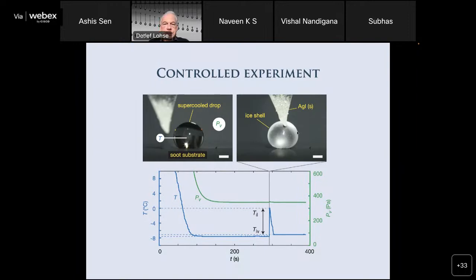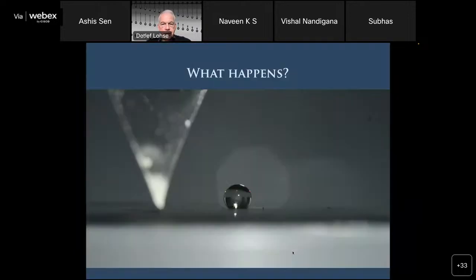And here you see the controlled experiment. We measure the temperature as a function of time. We reduce the pressure; here you see the pressure in green. We don't have to reduce it that much. I mean, it's not vacuum. It's say 400 Pascal. And then we see the temperature going down, staying constant, the drop being supercooled at -7 degrees. And at this point you have this phase transition, and then latent heat is released. Temperature goes up to 0, but of course later goes back down again. The whole process here is 400 seconds. So you really have to be patient.